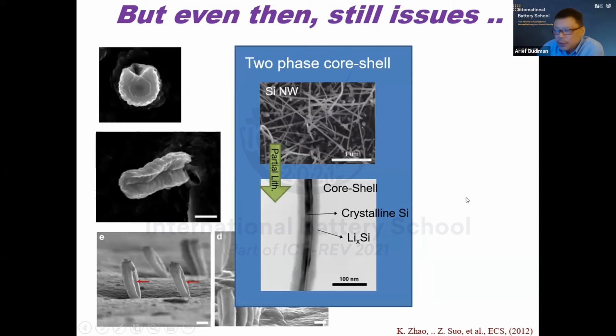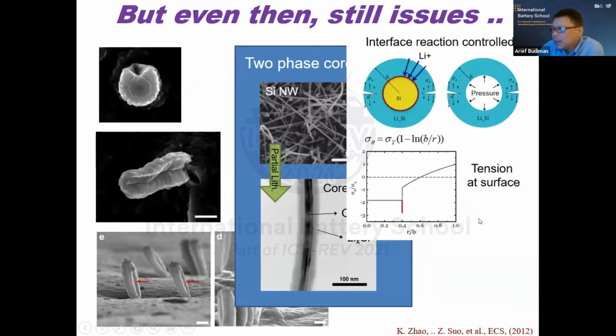So we're not going to go much deeper into this, but this has been studied, and people believe there is a core-shell model that explains this. Basically, what happens is that the lithium ion goes into the nanowire, and it starts developing very high tensile stress in the outer diameter and very high compressive stress in the inner diameter. So the outer part has a very high tensile stress, and because of that, it initiates cracks, and cracks grow, and that's what you see here.